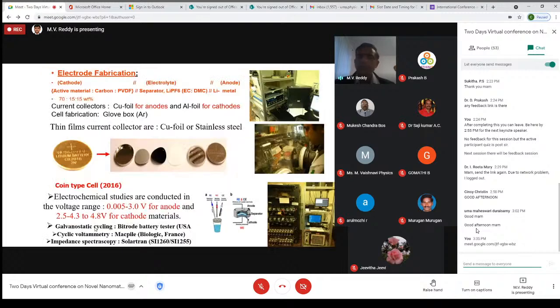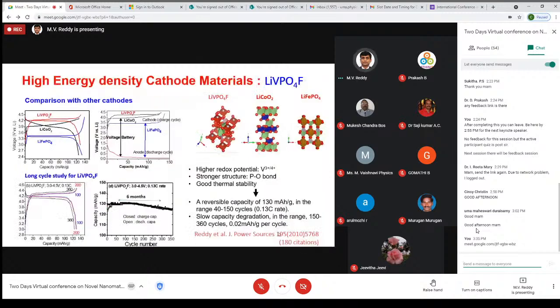So how can we fabricate the cell? You take, for example, this type of coin cell. You put your cathode or coated material here, then separator and lithium metal. Finally, the cell is ready, and we can do charge-discharge or electrochemical studies, etc. So we get the typical capacity with cycle number, or the charge and discharge profile.